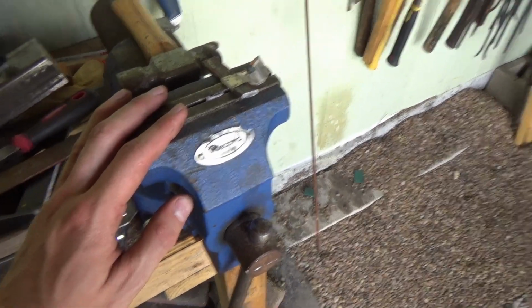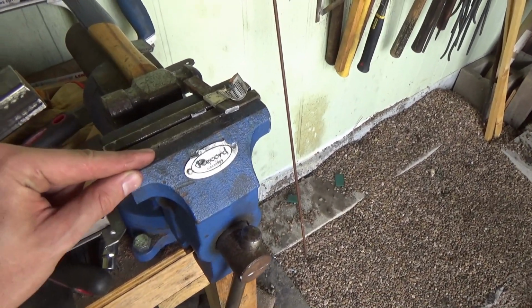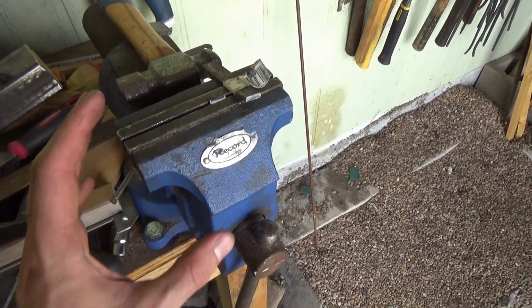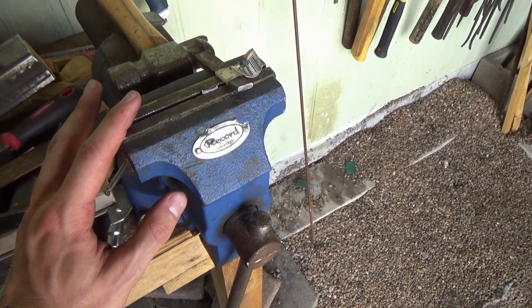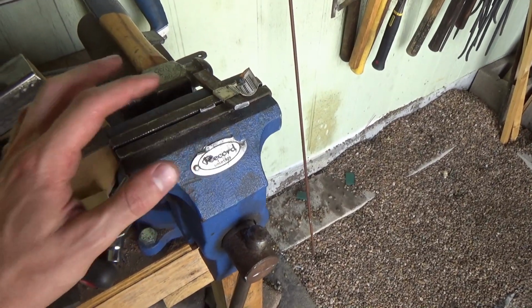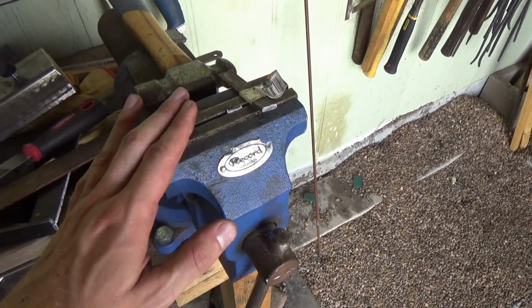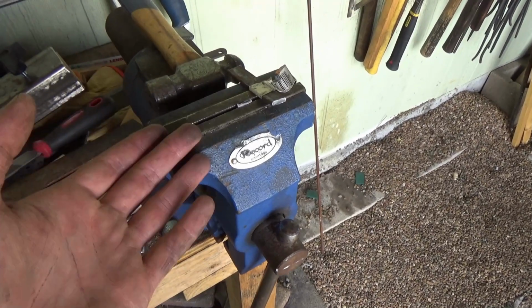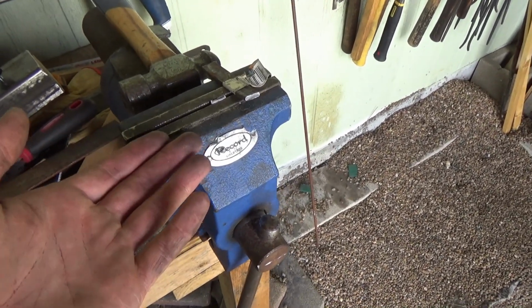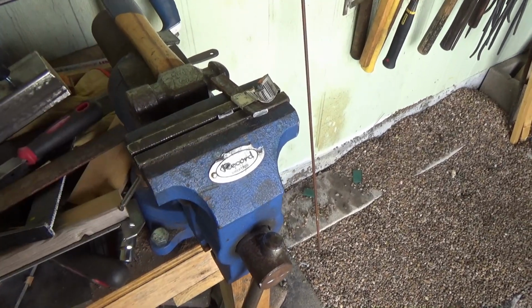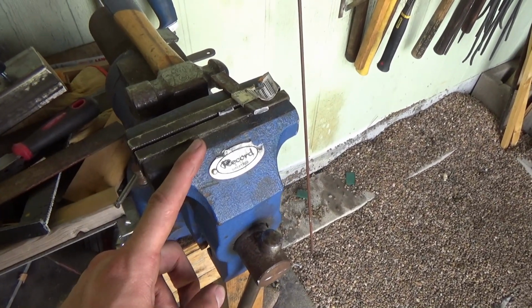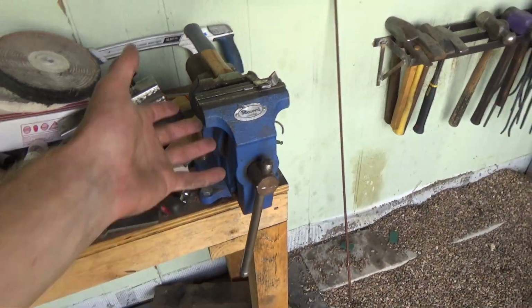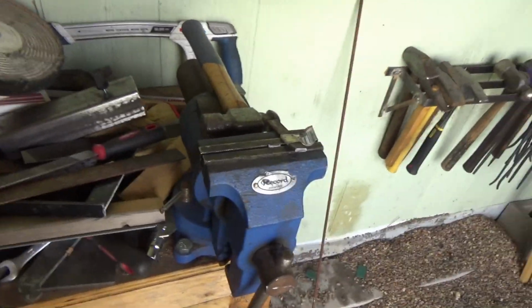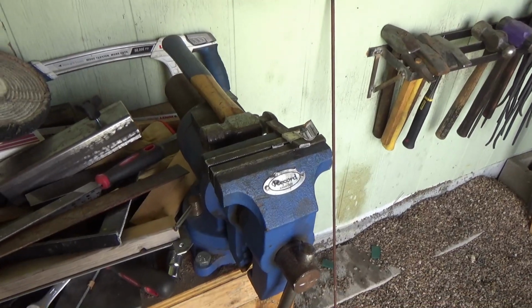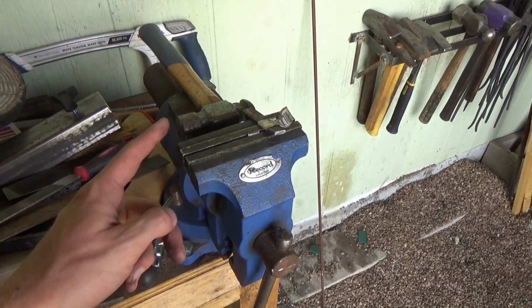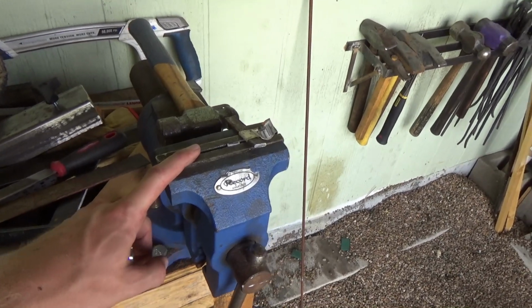And it won't fracture. Cast iron even more so, because if you get any stress from that process, it's additional stress, just like work hardening, that will cause problems and failures in cast iron, meaning that your weld will fail. Your steel plate that you just welded to your anvil will just pop off. That's not a good thing. So yeah, I could just weld a steel plate to the anvil, right? Yeah, you could. But do you have a welder? I have a welder, but it's a 110 volt welder, and it welds 1/8 inch steel.